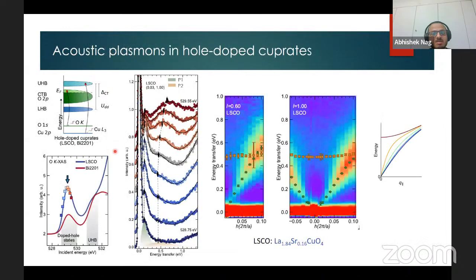The other part you asked about is this broad kind of feature. This is what you see in the incident energy, and it is quite broad. This feature appears from the bimagnon excitations in these systems. At the oxygen K edge, you can also excite bimagnons, and these appear at these energies. So this is present, but it is mostly non-dispersing, which should be the case for the spectroscopic signature of the bimagnons in these systems.